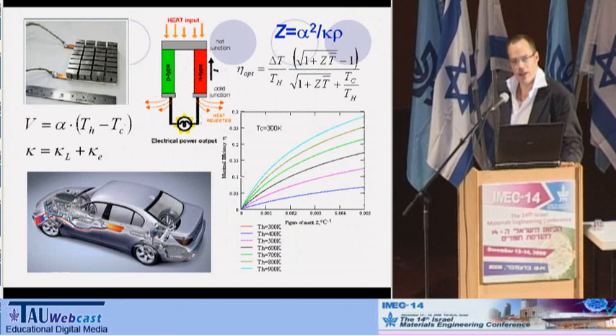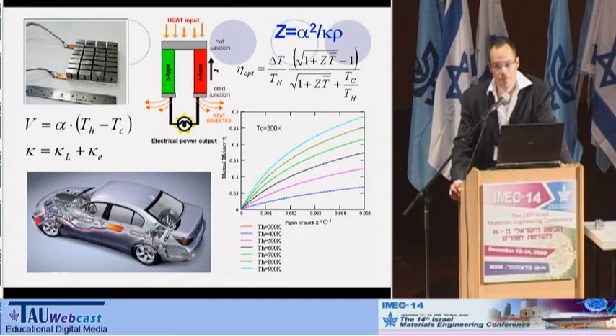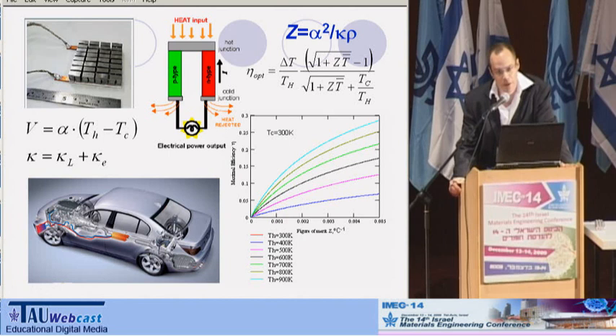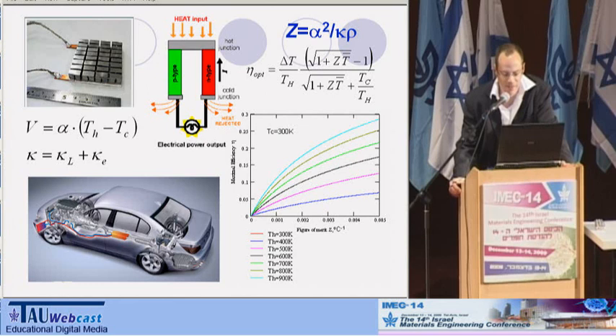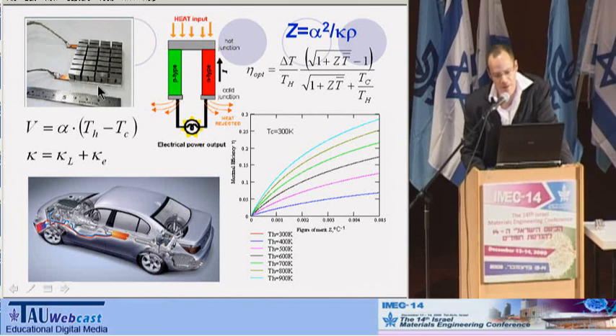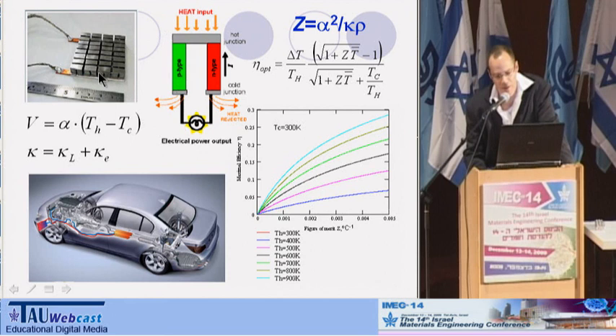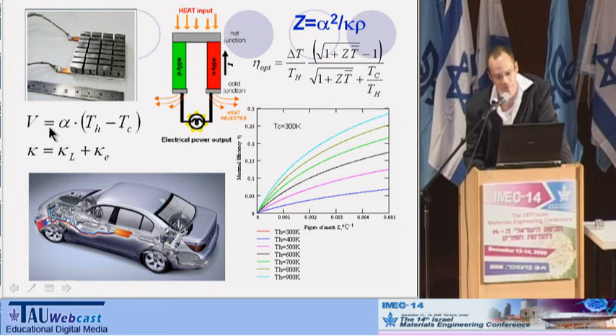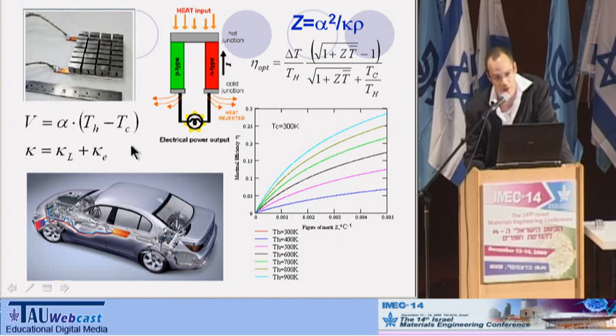Some background about thermoelectricity. Thermoelectricity deals with the interaction between thermal and electrical phenomena. The major application these days is the automotive industry. You can see here the BMW car. BMW were some kind of pioneers in this area for utilizing the waste heat generated in the car's engine in order to electrify several accessory electrical systems in the cars. Usually the conversion unit is based on several thermocouples, each one based on one N-type and one P-type semiconductor. The voltage obtained on the load resistance is due to the known Seebeck effect, where the electrical voltage is proportional to the temperature drop along the device — this is the hot side and the cold side temperatures.